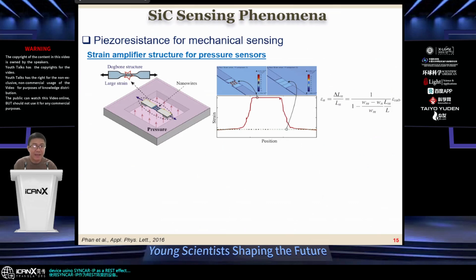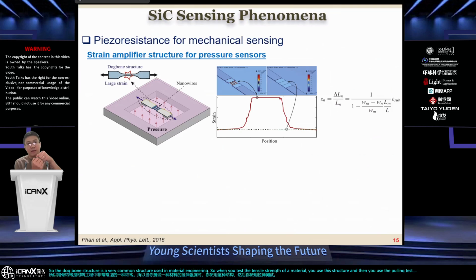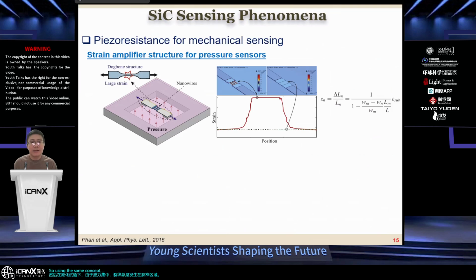So the gauge factor of p-type silicon carbide at room temperature is about 30, about 4 times lower than that of silicon. And to enhance the sensitivity, we can use this kind of dog bone structure. The dog bone structure is a very common structure used in material engineering. When you test the tensile strength of a material, you use this structure, and then you use a pulling test. Under the pulling test, the crack always happens at the narrow area because of the stress concentration. So using the same concept, we make a nanowire along with a nanoframe on a freestanding membrane like this. It forms a dog bone structure.